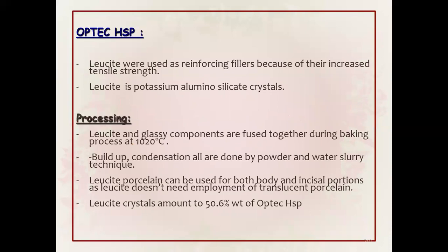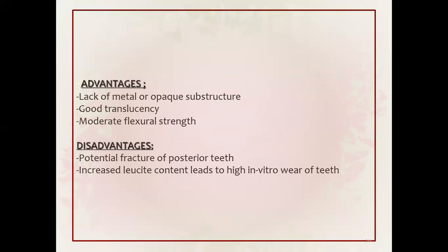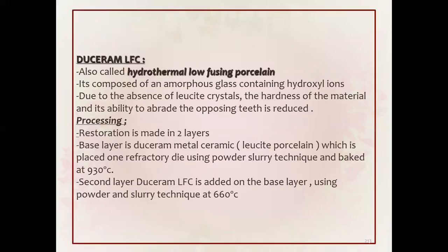Leucite reinforced porcelain — Optec HSP: advantage is lack of metal or opaque substructure for translucency, moderate flexural strength. Disadvantage: potential fracture of posterior teeth; increased leucite content leads to high in vitro wear of opposing teeth. Duceram LFC, also called hydrothermal low-fusing porcelain, is a composite of amorphous glass containing hydroxyl ions.